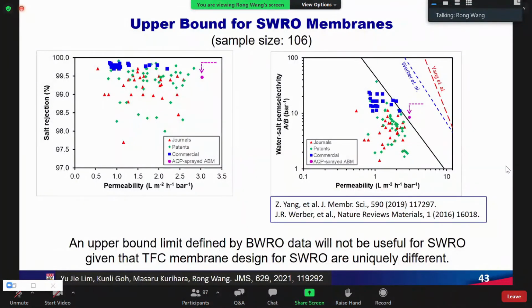So we think the upper bound limit defined by BWRO membrane data will normally not be useful for SWRO membranes. So we collected more than 100 data points from SWRO membranes to redraw these two figures: salt rejection versus permeability, and water-salt perm-selectivity versus permeability. You can see the upper bound now is here. This is only for SWRO. Our aquaporin-based SWRO membranes are located here. You can see it shows excellent performance compared with existing membranes in the literature and in the market.